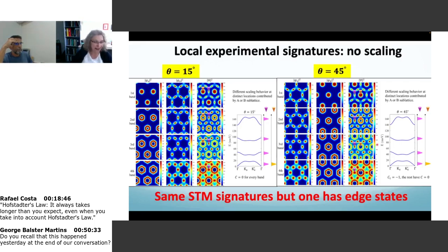I will have only one chiral state if I cut my sample here, because I will have a truly developed 0 Landau level, no more than one. And this 0 Landau level will have its corresponding chiral edge states, but there will be only one chiral edge. I will not have many. And this one will capture the states that have been captured by a particle in a box type of physics here. And again, since the particle in a box has a large spectrum separation because the box is deep, I will only see one of those.